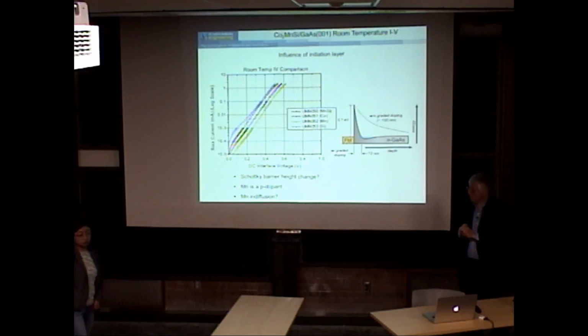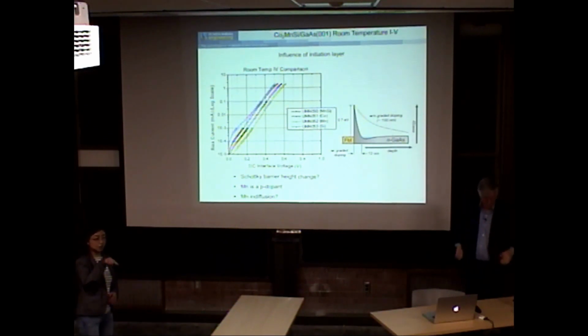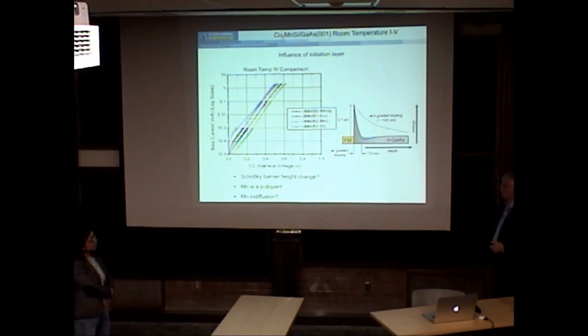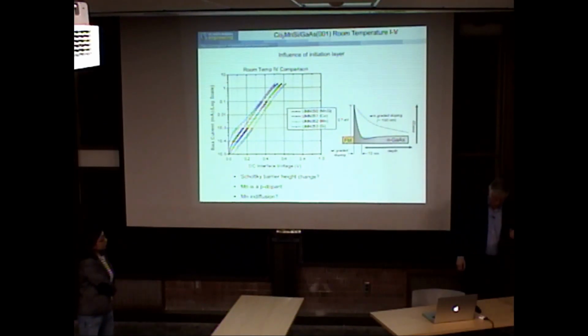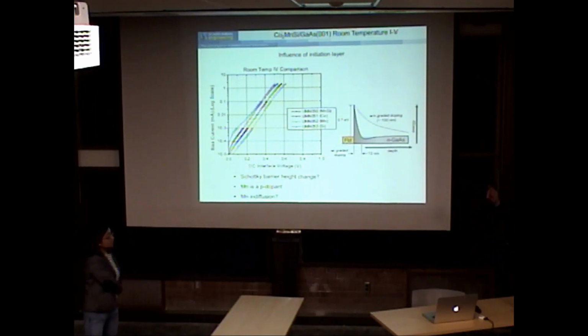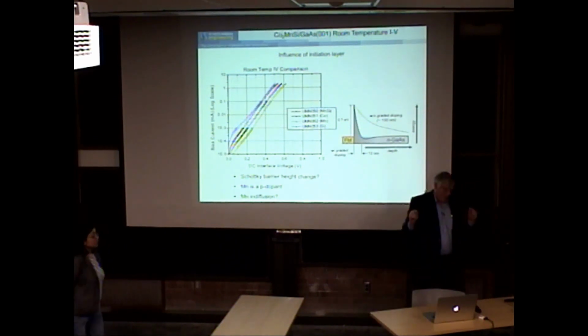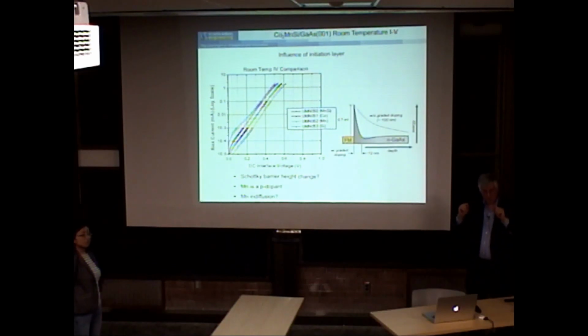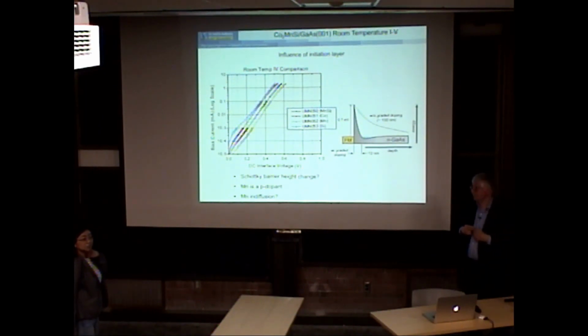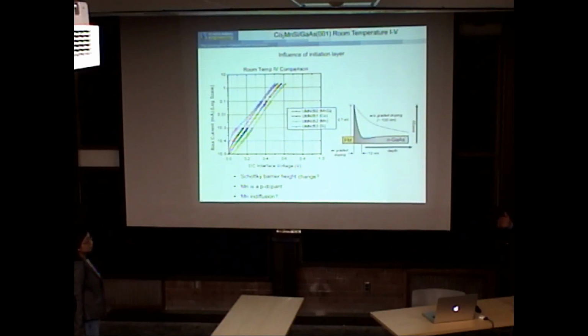Can you explain what it depends on, or not? Yeah, I think so. From the IV, yeah. Magnetoresistance. Oh, the magnetoresistance. So that dependence, the funny dependence that I did show you. That's a little harder because it's also very sensitive to the states that we've had as well. Because in some of the things we've done before with iron, the signs started reversing on us. So there are some interesting things happening at the interface as well. But the amount you measure also depends on how much current you have and how much polarization you're creating in the semiconductor compared to what's already in the bulk.